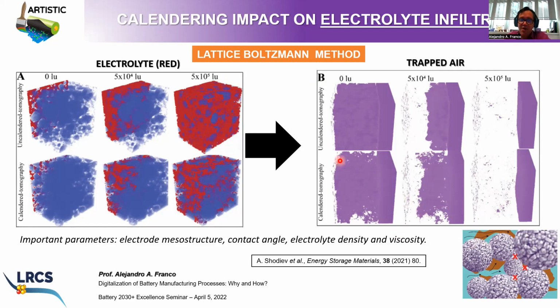This wettability phenomenon strongly depends, for sure, on the electrode mesostructure, as we see today, right? So if you have a calendered or uncalendered electrode, the speed of infiltration of electrolyte will be different. But it also depends on the contact angle of the electrolyte with the electrode. It depends also on the electrolyte density, and on the electrolyte viscosity. These are all the parameters that you need to take into account in order to optimize the infiltration process of the electrodes by liquid electrolyte.